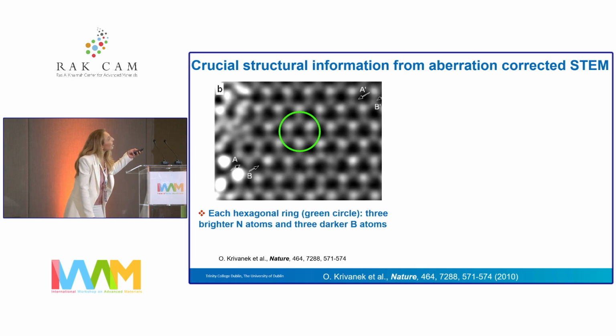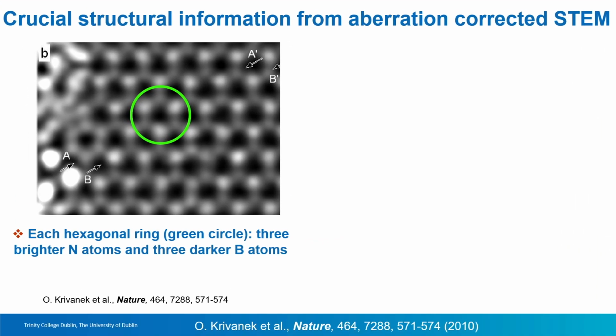What we did, for example, here with boron nitride, which is isostructural to graphene, where boron atoms alternate with nitrogen atoms, is a sort of atom by atom mapping. You can see these hexagons where you have the three nitrogens and the three boron atoms quite distinctively. But you can also see some deviations. For example, for the trained eyes in the audience, you could perhaps spot that in this hexagon, these atoms are darker than the nitrogen atoms.